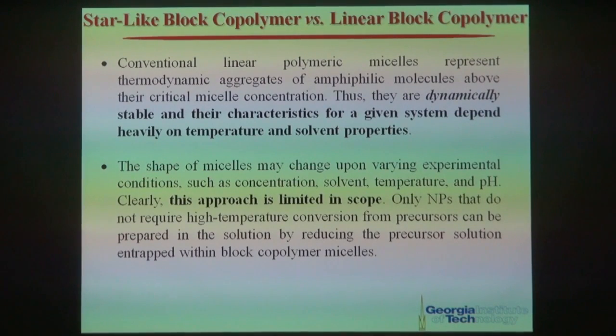Now here I want to briefly do a comparison to make it clear why we want to use star-like copolymer, not linear copolymer, because much research has been done to use linear copolymer as a nanoreactor to make particles. As I said early on, linear copolymer can form polymeric micelles, right? However, the structure of these polymeric micelles is dynamically unstable, and their characteristics for a given system depend heavily on temperature, solvent properties, and also pH and concentration. A little bit of variation in temperature, solvent properties, concentration, or pH can destroy the uniformity of your polymeric micelle composed of linear polymer chains. That's why this approach based on linear block polymer is limited in scope.